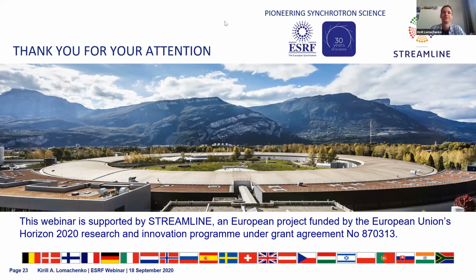Yes, absolutely, it is technically possible, and that's what we do routinely at BM23, for example, and at many other beamlines. It is possible if you have a dedicated oven that allows you to heat your sample. If you have it, and we do have it, so if you apply for beamtime at ESRF you can get access to it, no problem. You can absolutely make an in situ measurement heating your sample from room temperature to 500 degrees or 1000 degrees. The only limitation is your cell.